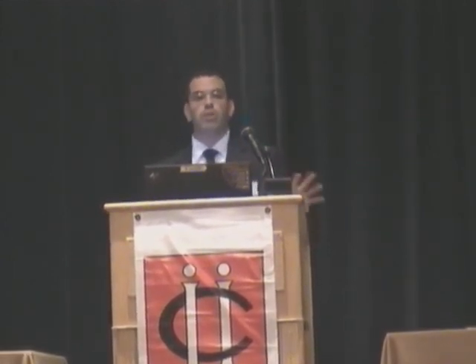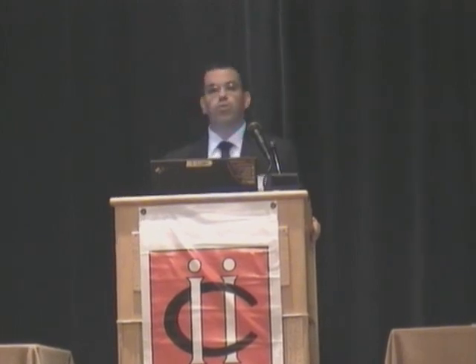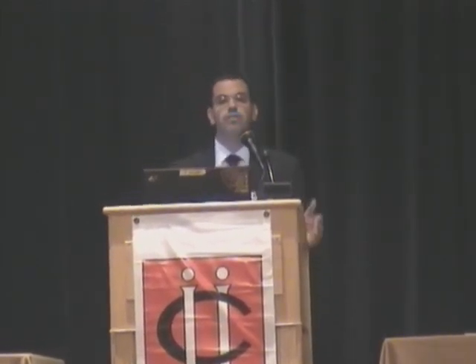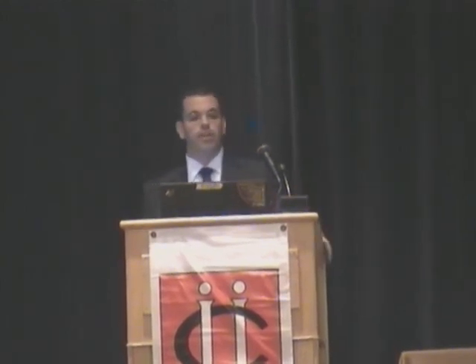And we said, okay, let's minimize the number of gates and put it on the first setup. Let's put the minimum gates we can. Okay, so we put only a couple of gates to hold the part so it won't fall in the shell. We go on thick sections, and we know we don't touch the thin walls. Modify the wax cluster frame to improve the drying process of the shell, allowing the fans, allowing the humidity to flow through the parts and dry it better. We took the top 20 and identified those 20 volume scrap generators, and we started running on them with an FMEA method, practically trying to realize what the problem is.